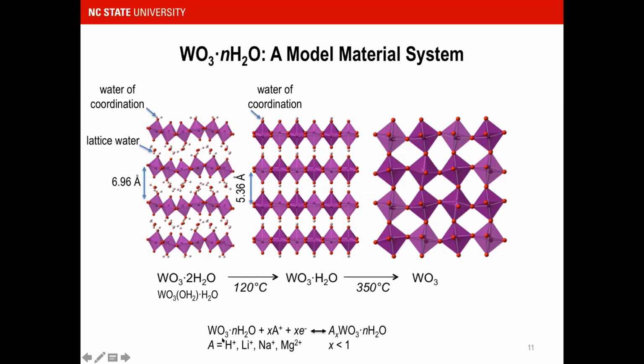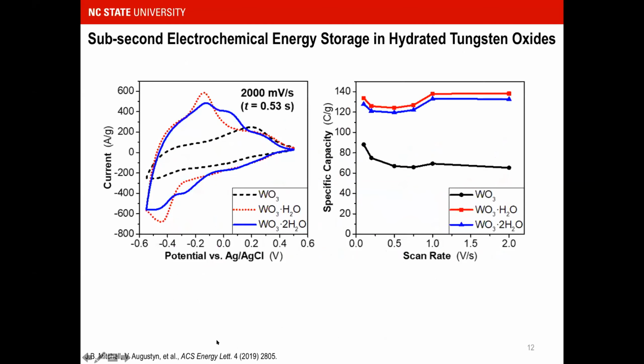And for our purposes today, I'm going to talk about our work with proton intercalation. And what's fascinating, what we discovered, is that when we have these hydrated tungsten oxides, we can see sub-second proton intercalation kinetics. And this is really incredible for an electrochemical energy storage material. Typically, the timescales that are measured for high-rate energy storage materials are 10 or 15 minutes. So here we're talking about fractions of seconds.